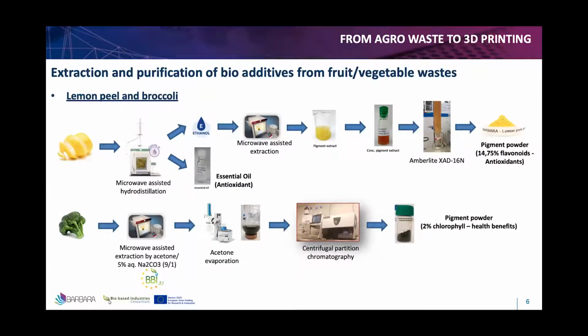For the extraction of natural dyes, biomordants, antimicrobials, and essential oils, microwave-assisted extraction, MAE, was used. This powerful technique let us obtain these bioactive compounds that were used as additives to the polymer matrix. From the lemon peels, two main different compounds were obtained. On the one hand, we were able to extract the essential oil to confer an intense fragrance and also antioxidant properties to the polymer. And also we were able to extract the yellow pigment powder.